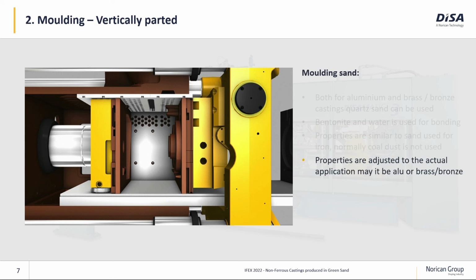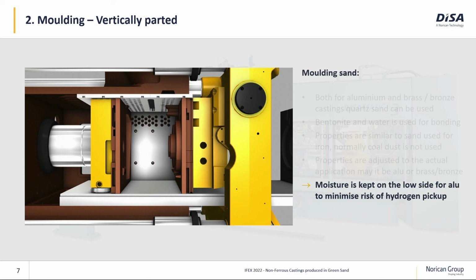Properties of the molding sand will of course have to be adjusted a little bit to the actual application, meaning are we pouring aluminum or are we pouring brass? In case we are pouring aluminum, we will try to keep moisture a little bit on the low side to reduce the risk to get hydrogen pickup. Are we talking about brass and bronze? We will try to keep the grain size at a lower level to reduce the risk of penetration.